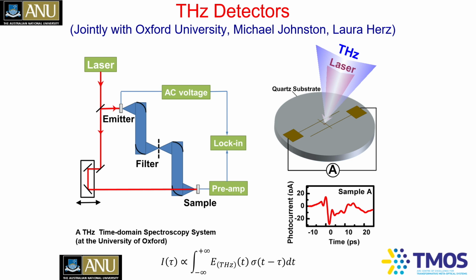This is work done jointly with my colleagues at Oxford University, Michael Johnston and Laura Herz's group. We make these nanowires, and this is the work of Dr. Kun Peng, my student. She transferred the nanowire onto a quartz substrate and then made contacts using electron beam lithography. She took these to Oxford University. You excite this nanowire with a laser pulse, and then you come back afterwards with a terahertz pulse. The photo-generated carriers from the laser are separated by the electric field of the terahertz pulse.